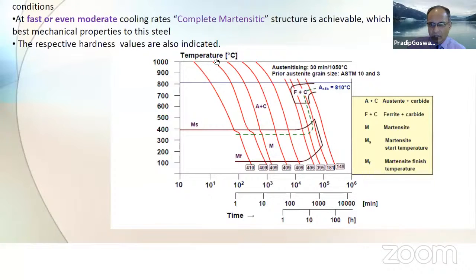one is going through a continuous cooling process, hitting this martensite start temperature and allowing the steel to cool to 100 degrees centigrade or below, and getting a hardness of 400 Brinell or more. This MS and MF temperature are critical things one has to keep in mind, and that will definitely figure when it goes through welding as well as subsequent heating and cooling cycles. I'll talk about those later.